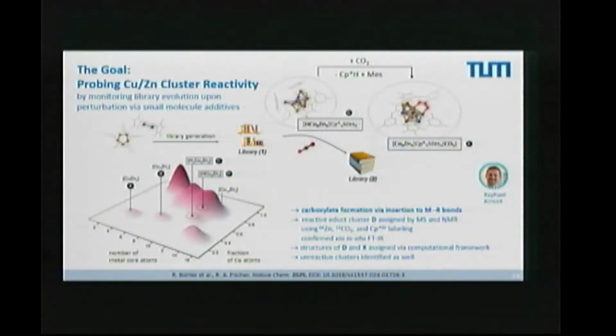So library generation creates us a starting point. Then we can put in CO2 without hydrogen. This is what is shown here, and we can see what happens. We see this kind of species, and we see this kind of species forming if we add CO2 to our primary library. And the calculation output from the partners tell us, in this case, when we have the CO2 around,